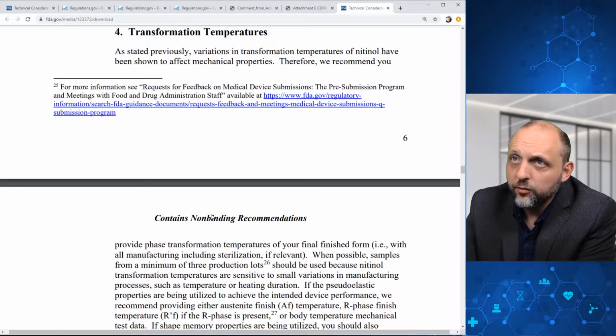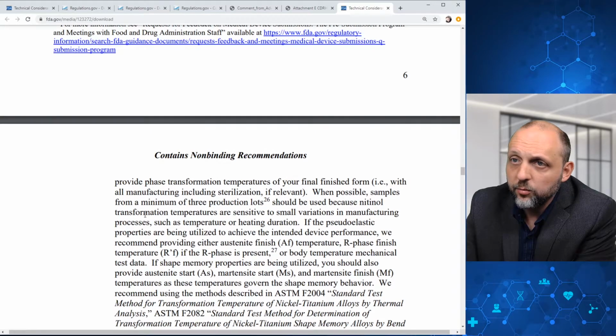And then in terms of transformation temperatures, FDA recommends you provide phase transformation temperatures of your final finished form. And when possible, samples from a minimum of 3 production lots should be used.